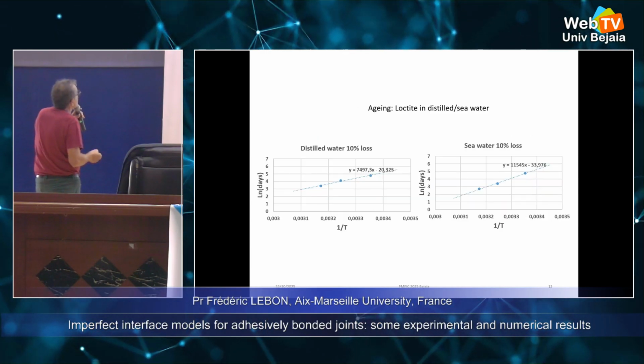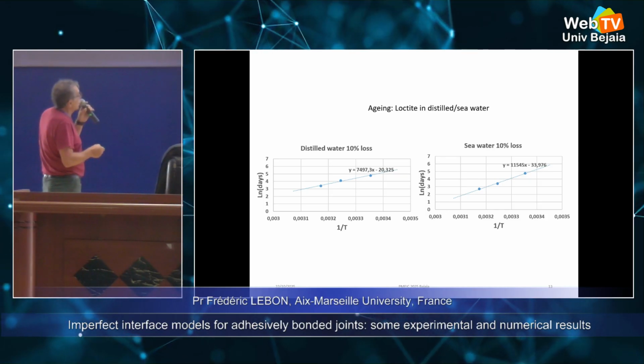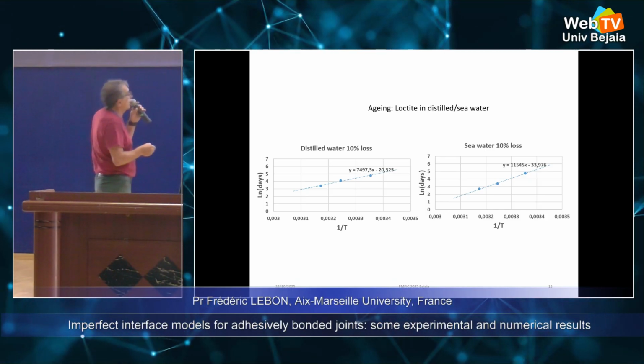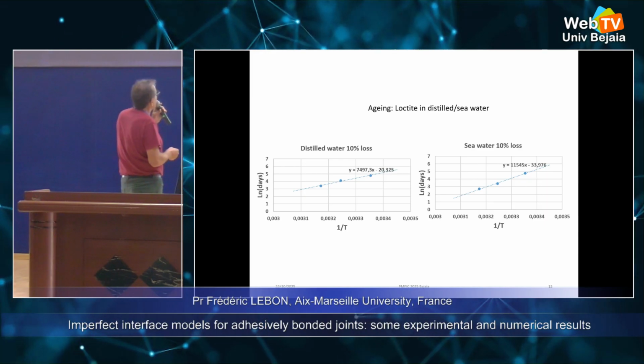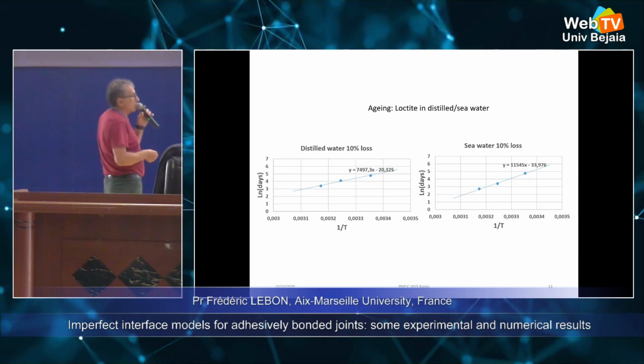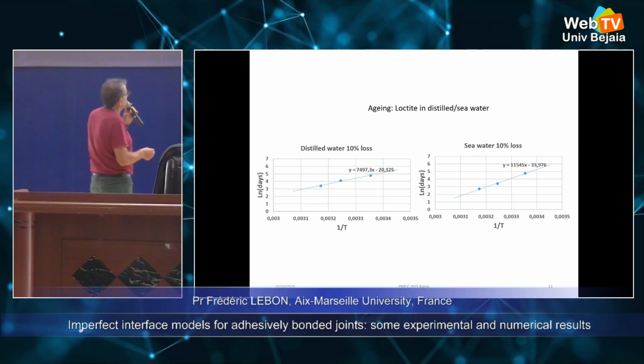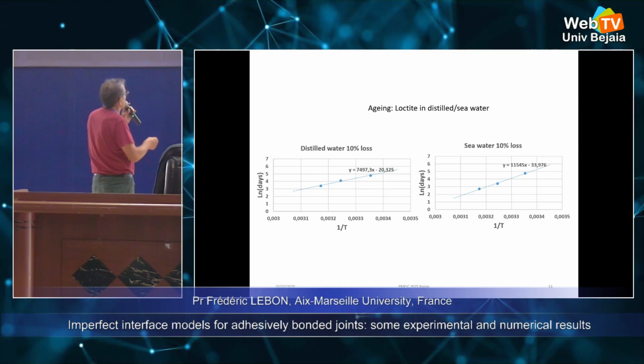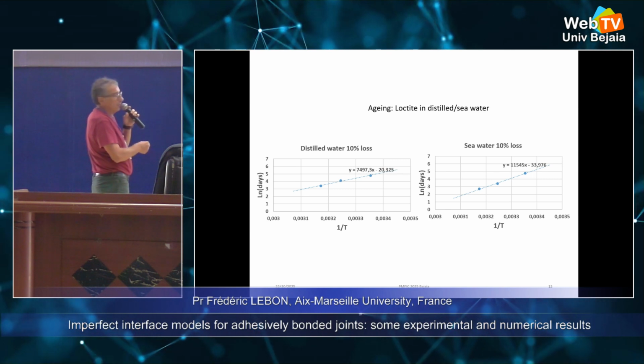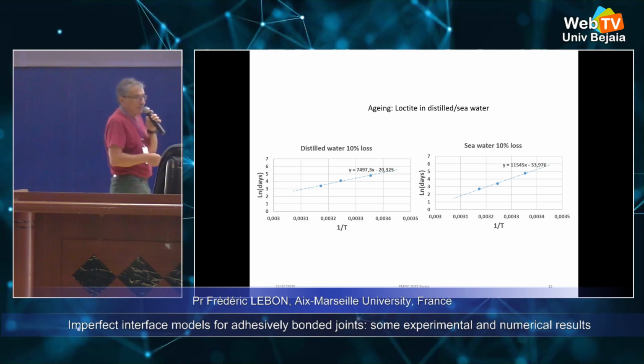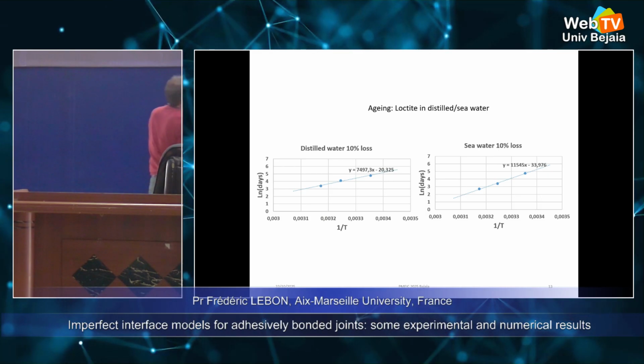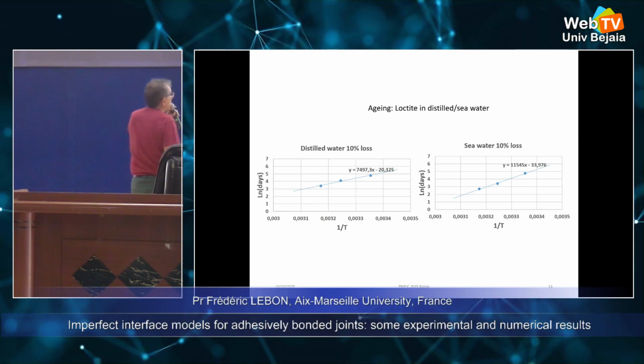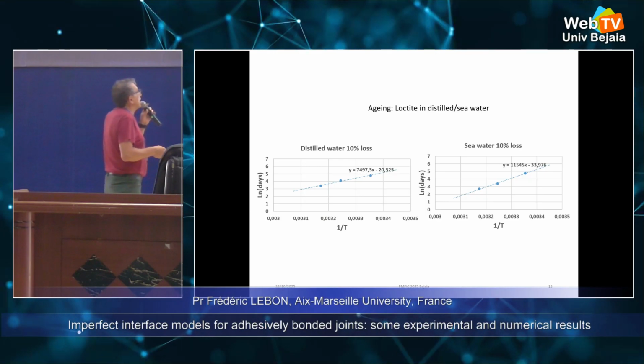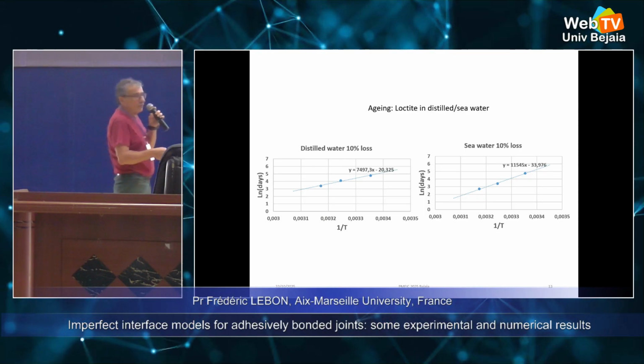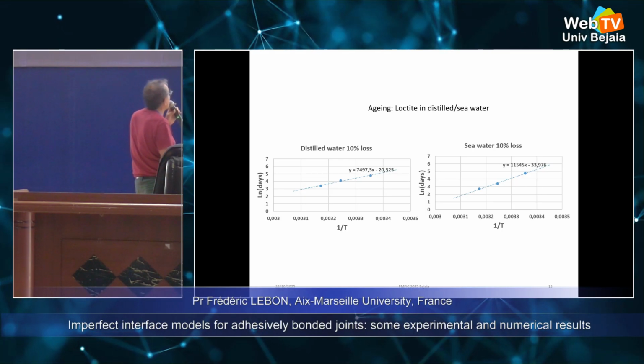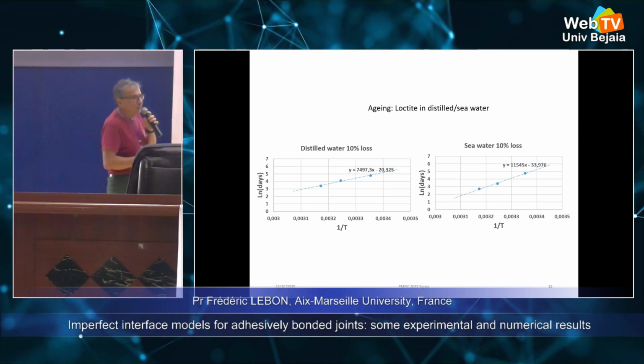Okay, so we can use another glue, Loctite, in distilled or seawater. We can obtain this kind of curve which is very close to the Arrhenius law. Here we have the temperature, and here we have the number of days, and we obtain a line which is classical. Okay, and so we can determine, at the temperature of the environment, the life of the glue.